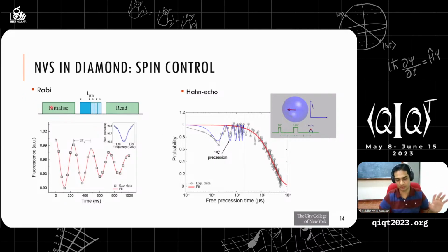In the previous protocol, the laser was on all the time, the microwave was on all the time. We were just changing the frequency, and the detector was detecting the counts at all times. What we are doing now is that we initialize this spin. We shine laser for a few microseconds. That is going to put that spin into ms equal to 0 state. So after this initialization, we are going to start in ms equal to 0 state.